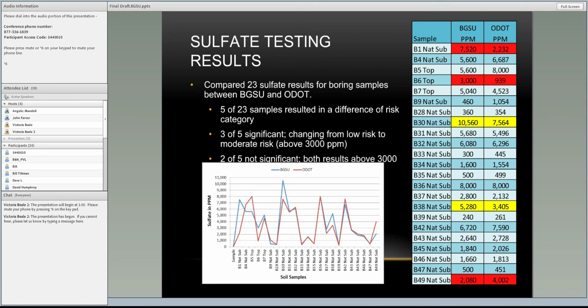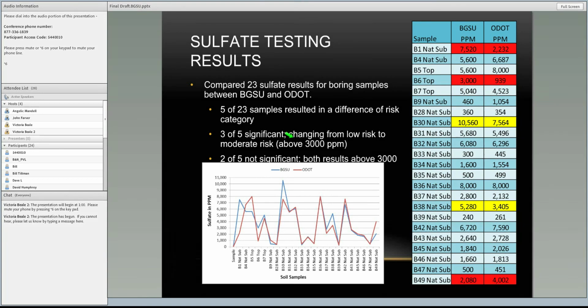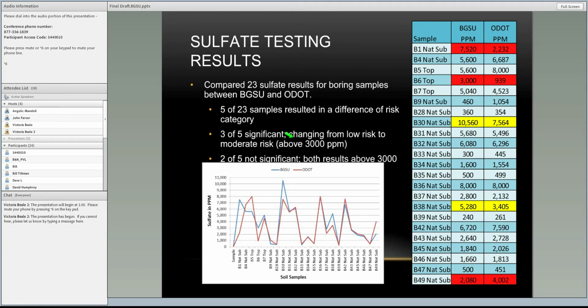And let me get the drawing function over here. The ones in red are these. There we go. The ones in red are the significant. Doesn't look like I can get my pointer to work here. There we go. Well, you see over here, ODOT's result was below 3,000 parts per million, where our result was above 3,000 parts per million. So those are significant differences. 2 of the 5 were not significant because both of our results were above 3,000 parts per million.